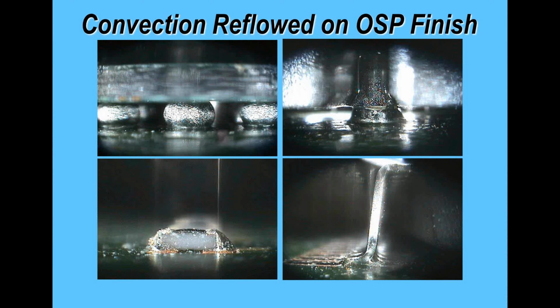Now in terms of visual appearance of solder joints, yes, the solder paste, the profile, the board finish, the time in liquidus, and of course nitrogen if it's convection, will all have an impact on the quality of the solder joints you're producing. But visually here are just a few examples. So these are all perfectly good, mechanically sound solder joints produced on OSP with convection reflow in air.